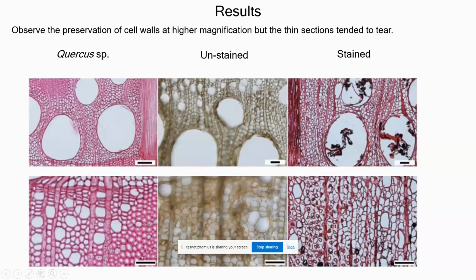In the first images you see the sound wood of Quercus, so how it looks normally. And here you have an unstained section of waterlogged archaeological wood of Quercus, and here a section stained with safranin and astra blue mixture that enhances the contrast in the cell wall and in the content of lignin. Here you see that you can reach quite high magnification and see also the features of cells, and in this case you see the cell wall almost disappeared, and only the middle lamella is still there.